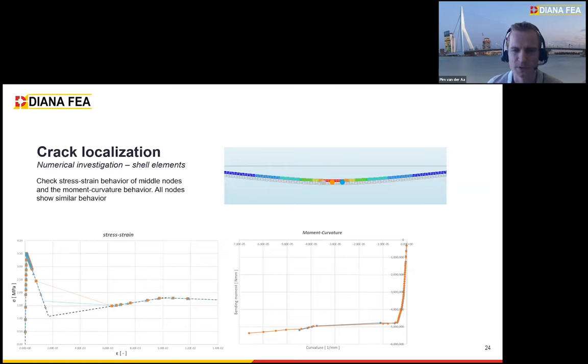That's basically also what you see in a typical moment curvature diagram. For this cross-section, you can make a moment curvature diagram, which you see on the right bottom, which usually goes initially with a linear elastic branch. Then you see a small deviation, which is induced by the initial cracking. And then it goes to a more flat part, which is initiated by the yielding of the reinforcement. And what you see is actually that for different points on your shell element, the same moment curvature diagram will be followed. And this is also expected because the strain distribution over the height, let's say, of your shell element, so in the out of plane direction, should always remain linear.